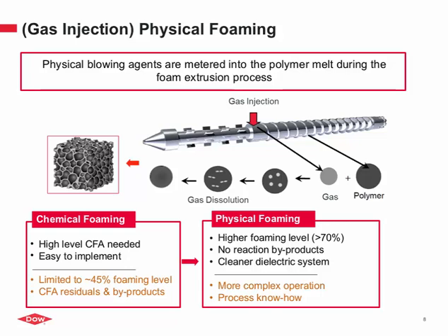And then what happens, there is a gas-polymer mixture, and as the material is driven to a high pressure, there is dissolution of the gas in the polymer melt. So you have a homogeneous solution that has the gas, and as the pressure is released at the exit, then the foam expands, and I have pictures to show that. So this is the gas injection process, which is generally used for the topic that we are discussing today.